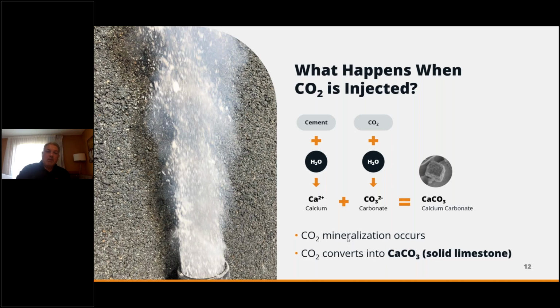So when we inject CO2, what essentially happens is it reacts with the cement particles and actually recalcinates a portion of that cement back to calcium carbonate. And so when you're manufacturing cement, as many of you will know, you're basically heating up that limestone into clinker at about 2,600 degrees. And when you make that, actually, there's a chemical reaction that creates CO2 at the same time, plus the energy required that drives that. So potentially, if we're able to reduce a portion of the cement from a mix design, we're able to have a fairly positive environmental impact. And so that mineralization drives that conversion back into calcium carbonate or limestone.